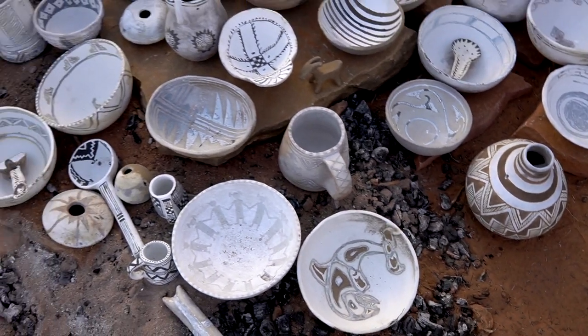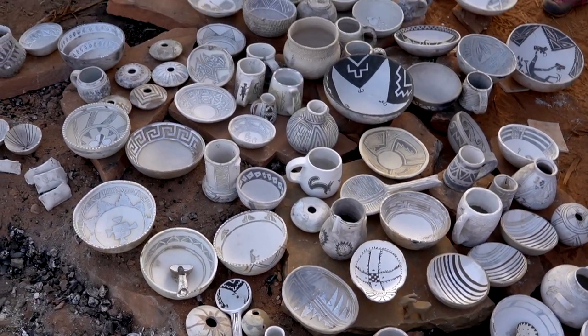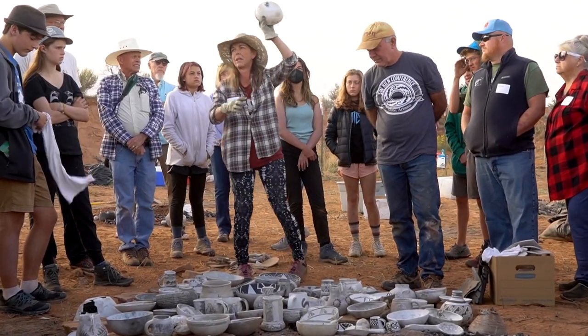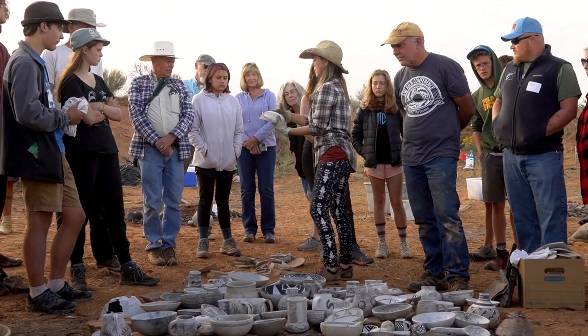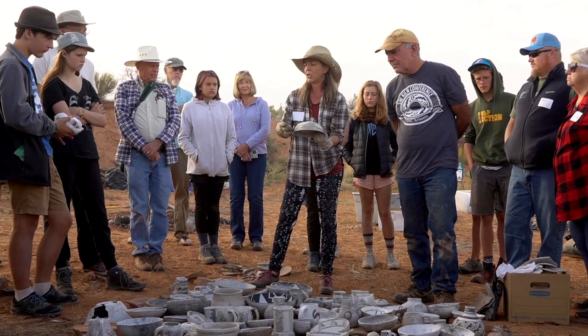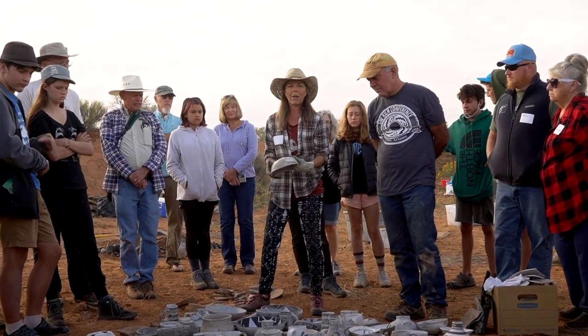Pick up a nice piece of an oxidation. Let me have that one for just a minute. So definitely here is a smoke cloud, right? So a piece of carbon came down on that and it couldn't get any oxygen right here. But this other bright yellow stain, that tells me two things. It tells me one, it got a little oxygen bump right in that end. And I could see all these pots, right, just before I panicked.